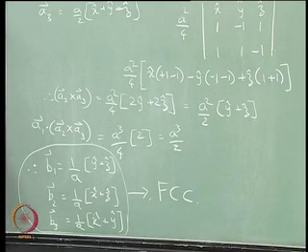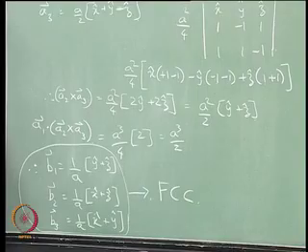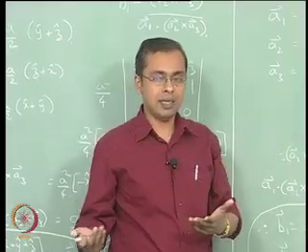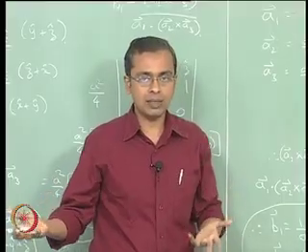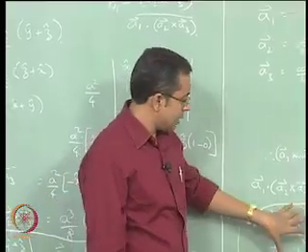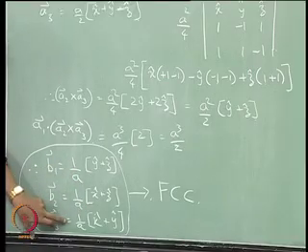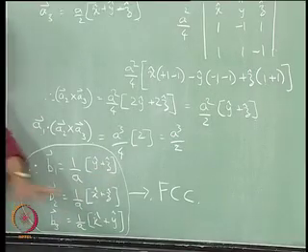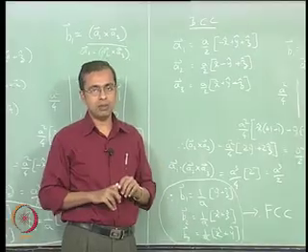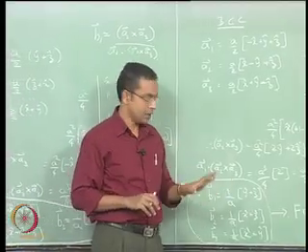So if you have a real material which is body centered cubic, and you want to represent it in reciprocal space so that you can see its interaction with waves, then its representation in reciprocal space will have some dimension 1 by A, and the layout of those vectors will be identical to a face centered cubic material, okay. So that is what it is.